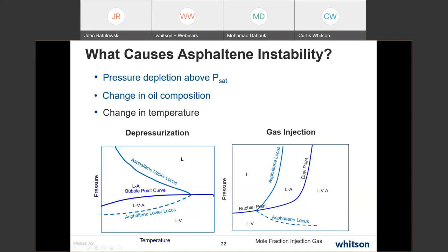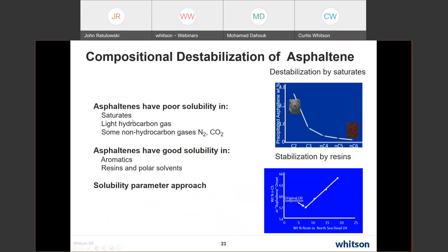All right, so asphaltenes have poor solubility in saturates like hydrocarbon gases and some non-hydrocarbon gases like nitrogen and CO2. They have good solubility in aromatics, resins, and polar solvents. And a lot of times people use a solubility parameter approach in order to model this type of behavior. And you can see over here, there's just a couple pictures where we added resins into an oil and we saw, as expected, that the solubility for asphaltenes increased. And we can see here that really the lighter molecular weight gases, C2 and C1, C3, have a much more destabilizing effect on this than something like a hexane or heptane.